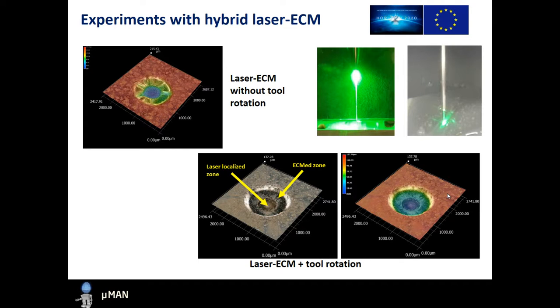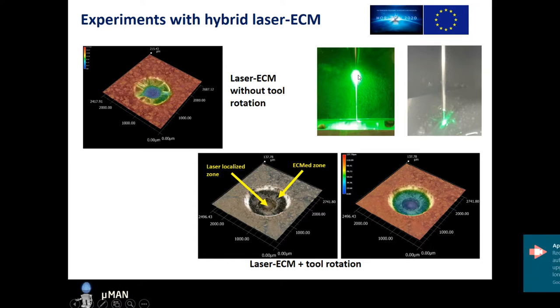These are some of the initial experiments we did on hybrid laser ECM in the framework of the Microman project. On the left-hand side, we can see a point removal experiment on Inconel IN 718 material without tool rotation. On the outer periphery we have electrolytic flow effects, and in the center is the laser localized ECM zone. On the top right-hand side, this is not a perfectly aligned process, where we can see some scattering at the tool electrode, but this one is a perfectly aligned process. The bottom two are cavities which were machined with laser ECM. In the center, we can see that we have laser localized process zones. I will discuss this in part 3 of the video.